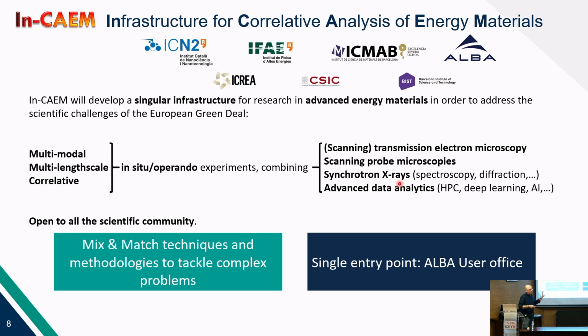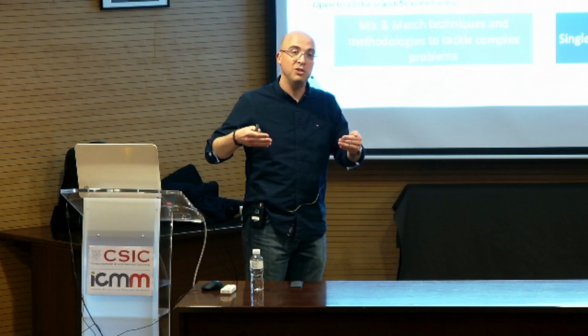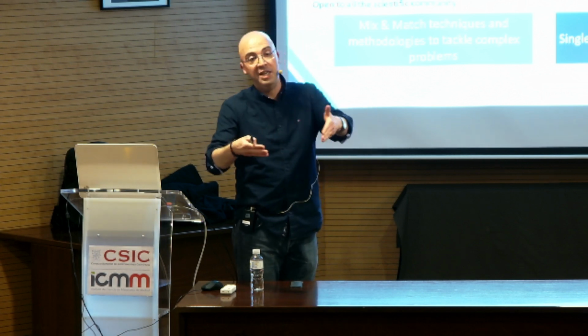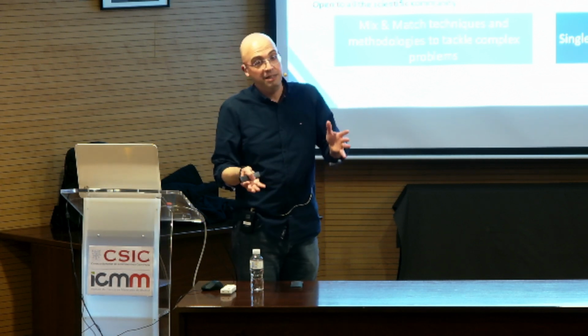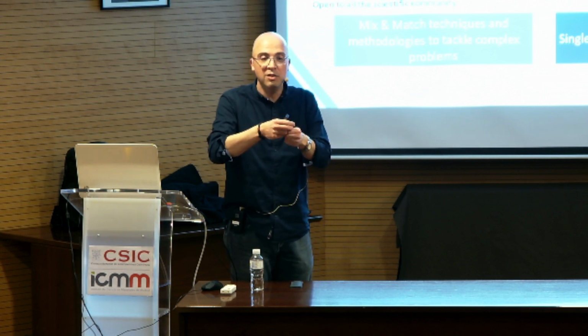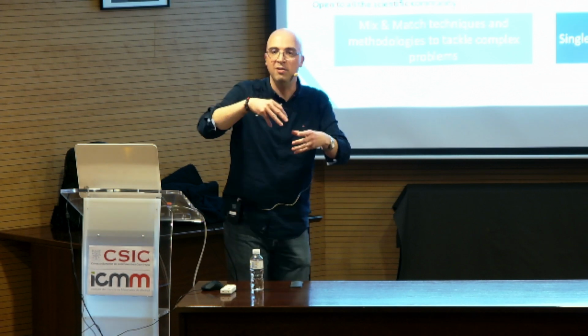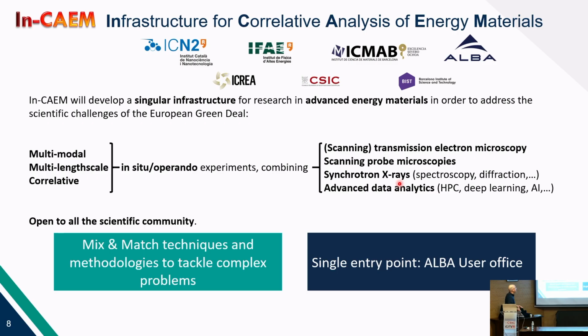We need to adapt. At the moment, there are 4 beamlines that we are trying to adapt in order to work with the same holder. And the first problem: in the microscope, you work with picometer resolution, but in the synchrotron, you have a beam that is like 30 microns. So sometimes the window that you have in the TEM is too small for the synchrotron beam. What we are doing now is adapting the beamlines, but also adding mirrors in order to focus the beam and make it around 10 microns, less if we can, in order to get inside the window and not detect the things that are around, okay? So this is the idea. We are working on this, and by next year, all this should be solved.